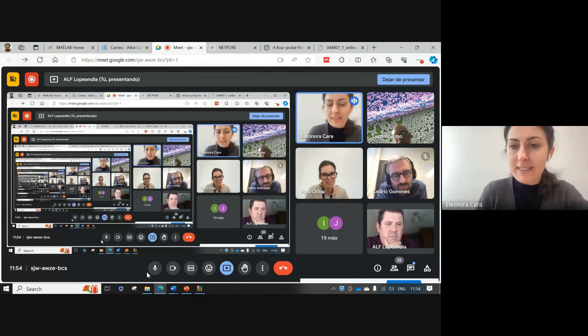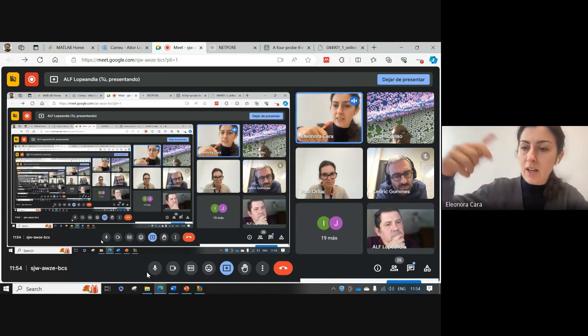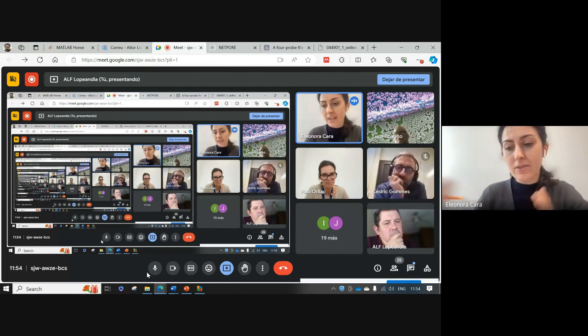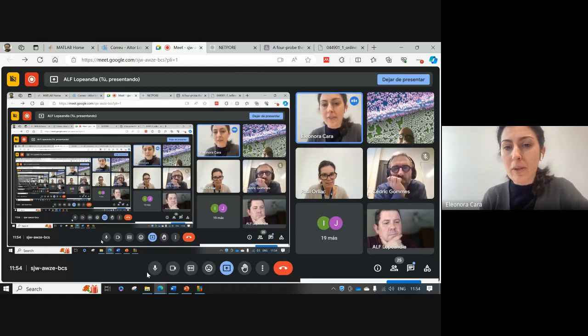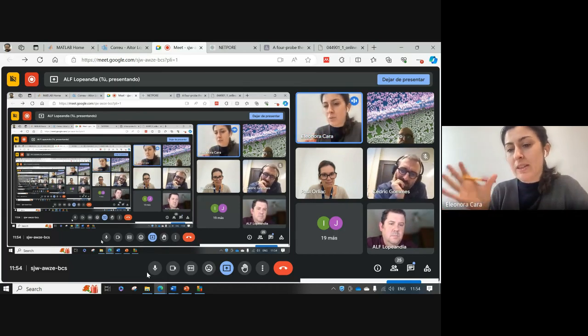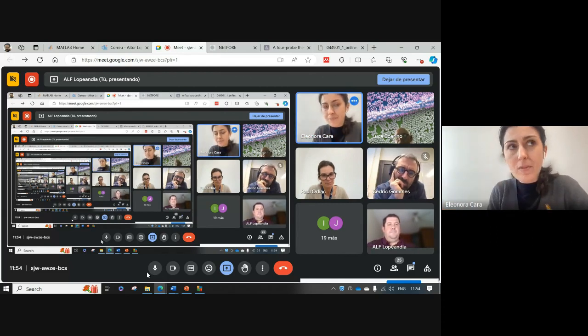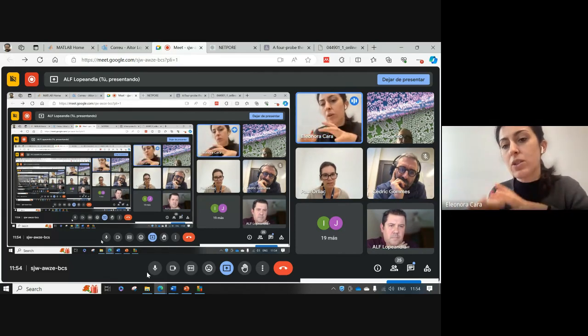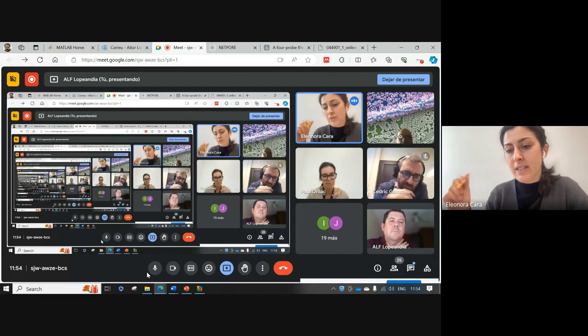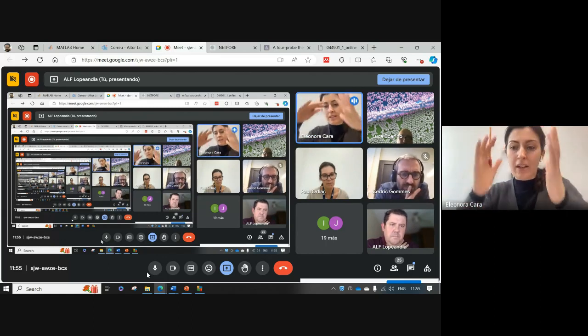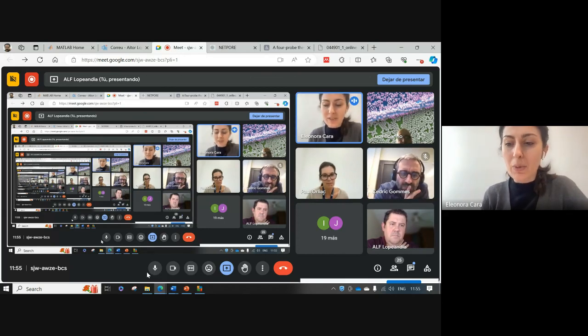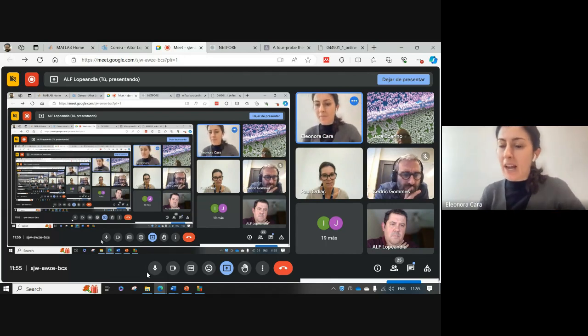So let's say that the wires are quite delicate during the process that my colleague Matteo Fretto is doing of taking one single nanowire and placing it on this platform that UAB is developing. They can break due to stress that the nano manipulator is inserting on the nanowire, and we have not explored the mechanical stability or any difference between the pristine nanowires or the coated nanowires. Currently, we are doing with CLT in Grenoble TEM tomography of the infiltrated nanowires, so the nanowires coated with the zinc oxide, to understand how much of the zinc oxide has actually gone inside the pore and what is actually coating outside of the nanowires. So we have not really a measure of any mechanical parameter.